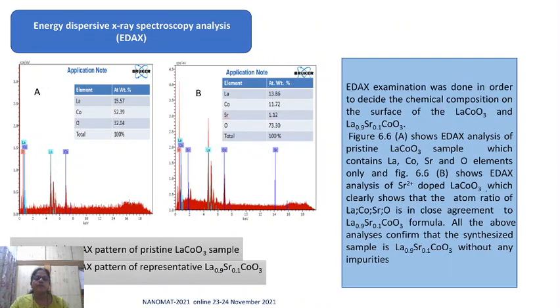Energy dispersive X-ray spectroscopic analysis was done in order to determine the chemical composition of the surface of LaCoO3 and Sr doped LaCoO3. From figure A, you can see that the LaCoO3 sample contains La, Co and O elements only, while figure B shows the Sr doped LaCoO3, which clearly shows the atomic ratio of La, Co, Sr, and O are in close agreement with the formula La0.9Sr0.1CoO3. All the above analysis confirmed that the synthesized sample is LaSrCoO3 and does not contain any impurities.